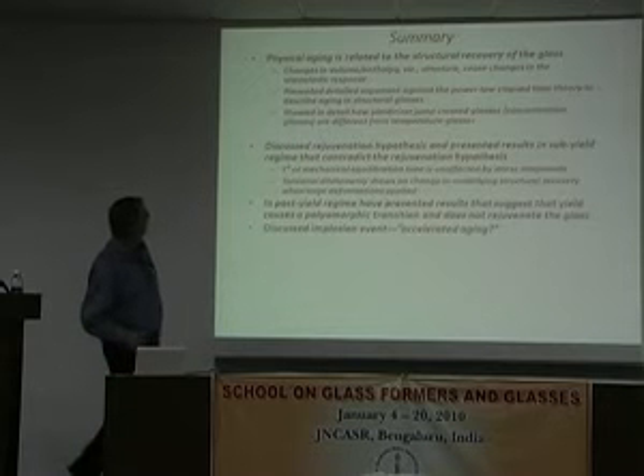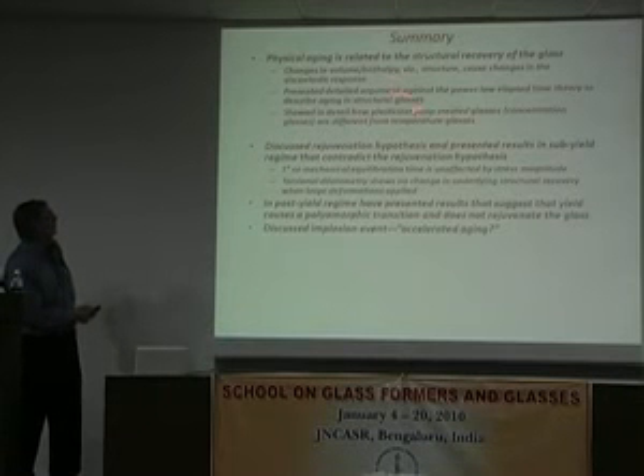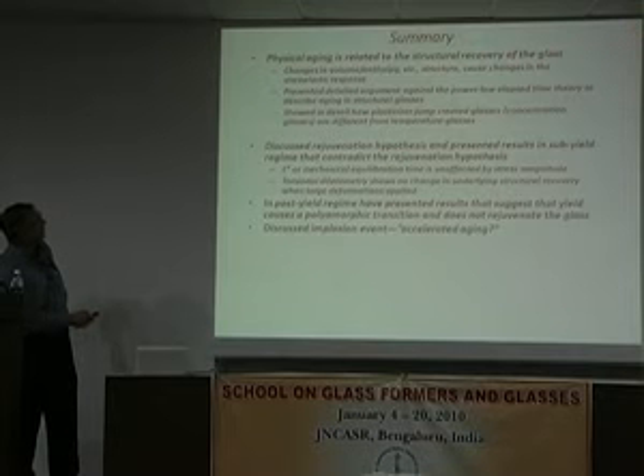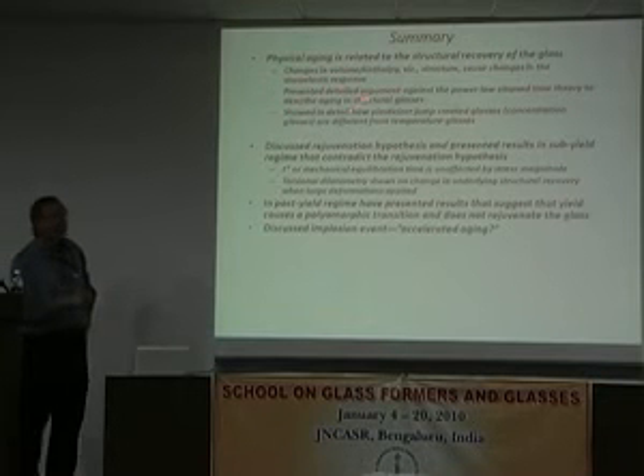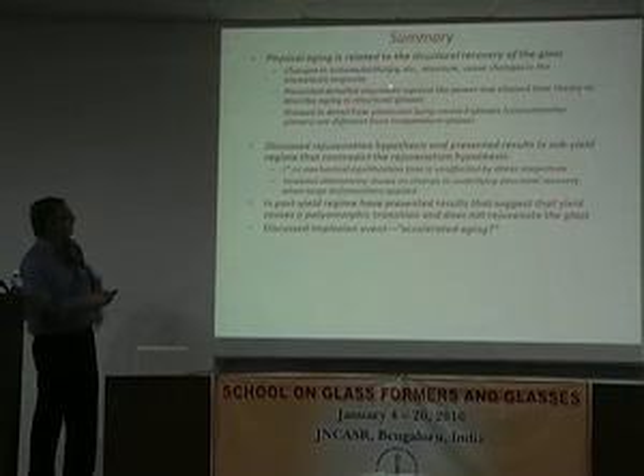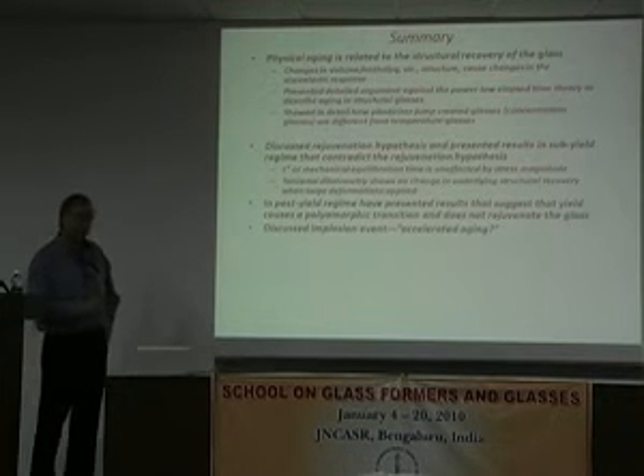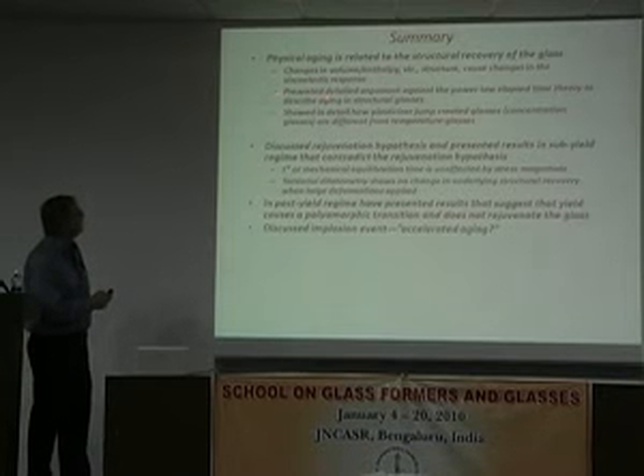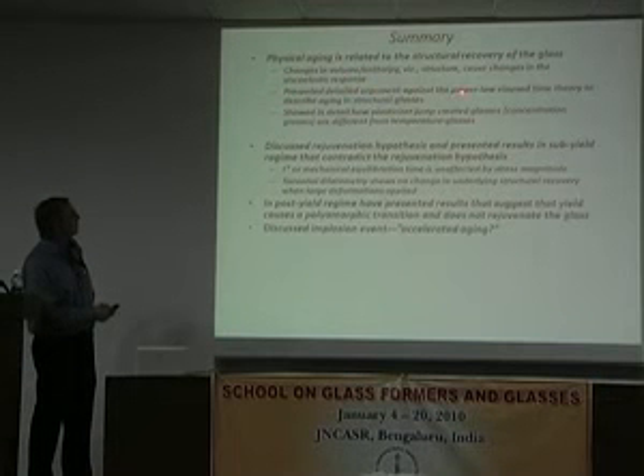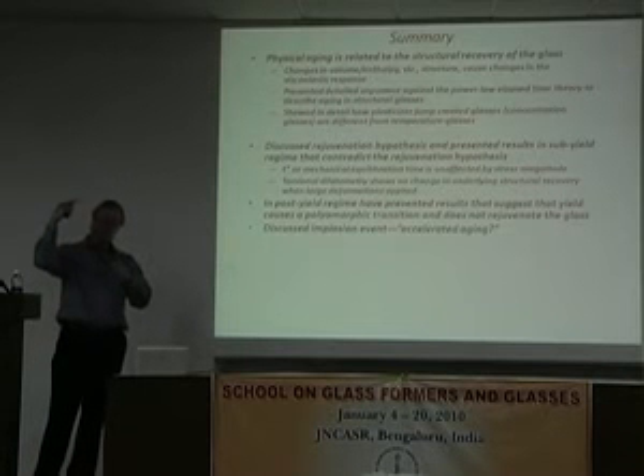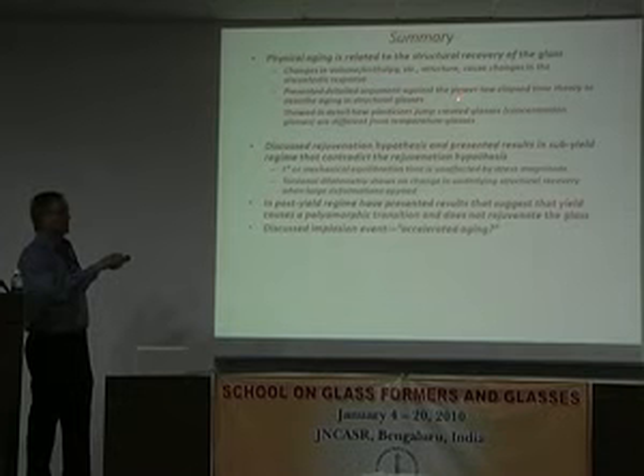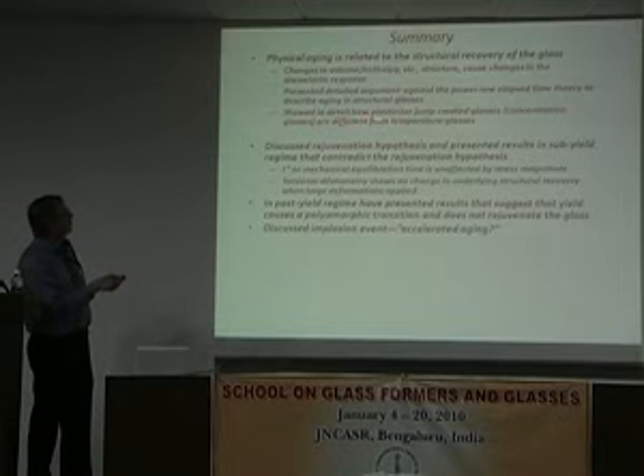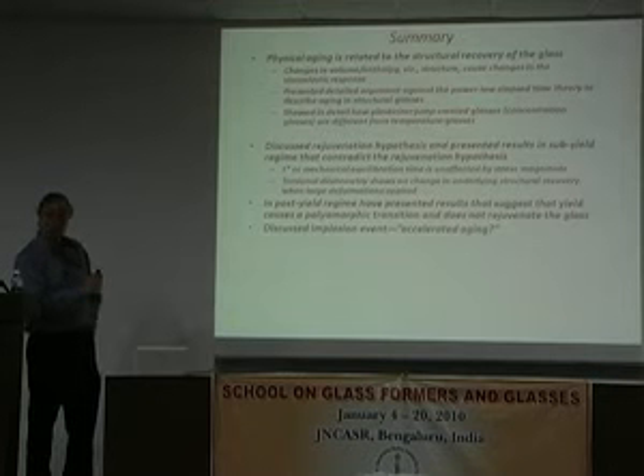So just to summarize, I think we know physical aging is related to the structural recovery of the glass. Changes in volume or enthalpy or other internal parameters, i.e. the structure, cause changes in the viscoelastic response. That's what I mean by aging. I presented a detailed argument against the power law elapsed time theory to describe aging in structural glasses, or at least defining its limits, as sort of where we run experiments, of course, and showed in detail how pressure jump experiments create glasses that are different from temperature glasses.